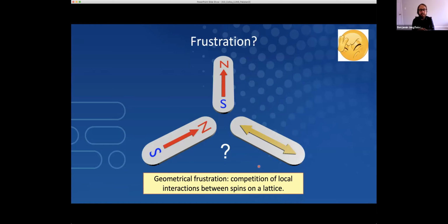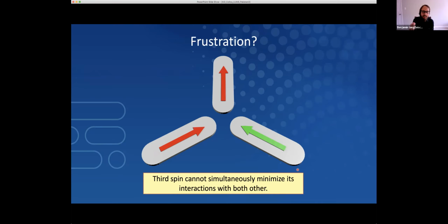What does it mean? Well, let's assume we have this triangle lattice with these nanomagnets, as you can see with South Pole and North Pole. Geometric frustration now means this third spin doesn't know how to align. You can think about it, and the conclusion is that the third spin can never simultaneously minimize its interactions with both the other spins. It can align like this: one vertex is happy, one is frustrated, and the same goes for this orientation. So there is some geometric frustration in the system, which leads to a high degeneracy of states, and this makes these materials very, very interesting for various reasons.